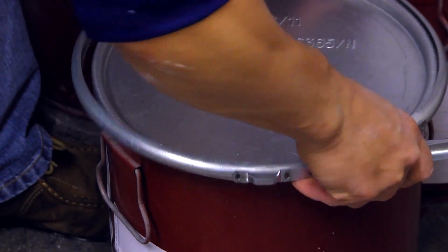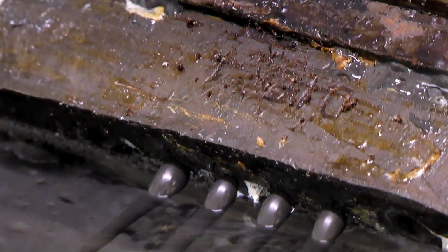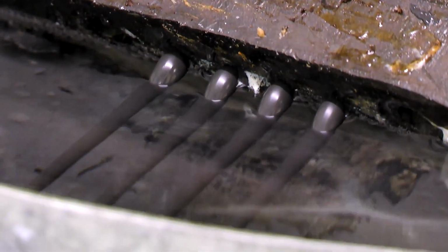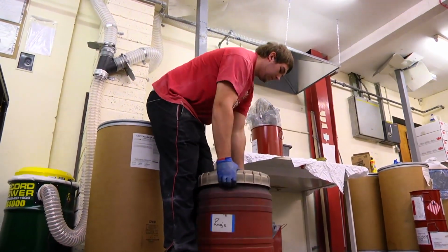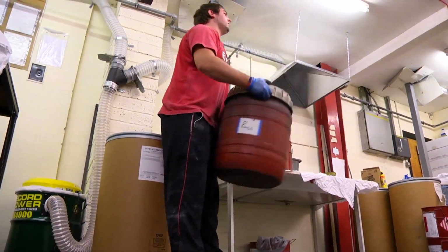In compounding, we can put levels of tungsten into the polymer, which allows the line to sink faster. And because polyurethane is so tough and so durable, it allows us to put real high levels of tungsten into the material. We can even get 90% by weight of tungsten into the polymer.